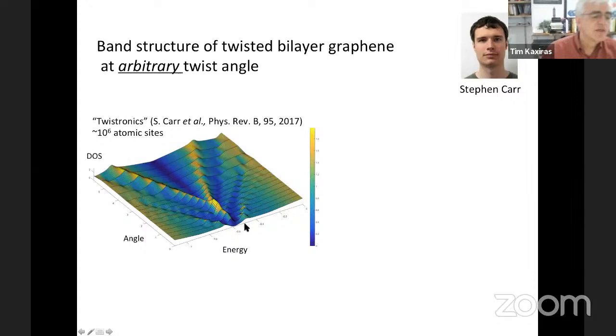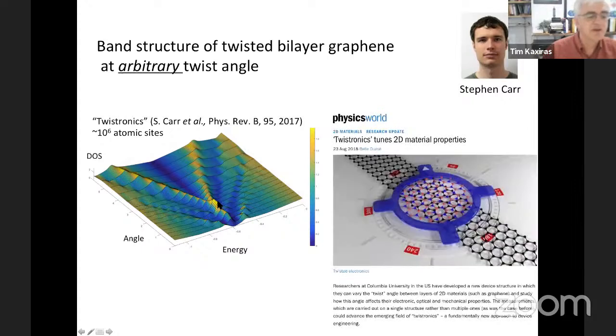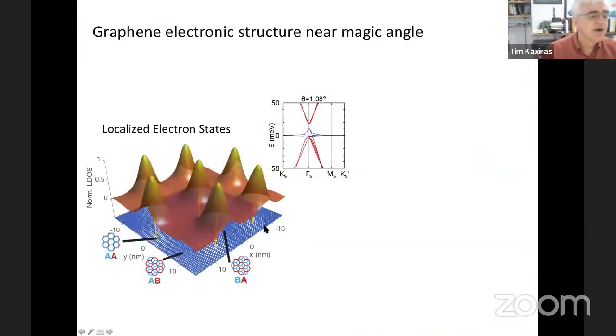density of states with the small humps here, the small increases here, the Van Hove singularities that I mentioned earlier, which are far from the Fermi level. But as you decrease the angle, you can get very high density of states right at the Fermi level. And these are the flat bands, the effect of the flat band. So we named this effect twistronics, and then it caught on. Magazines like Physics World picked it up, and now it's quite popular, and it even has its own Wikipedia entry.